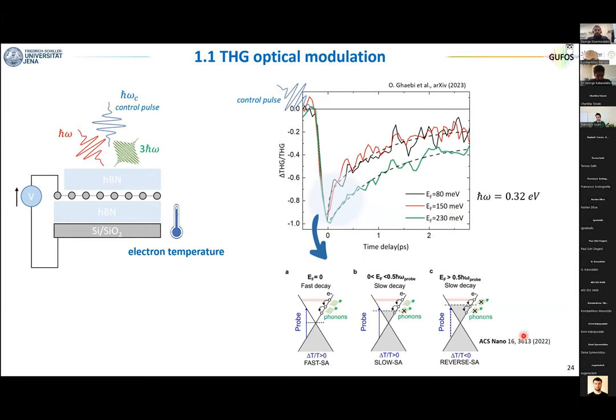This is again a work that we did with Giulio Cerullo. And the idea is the following. When you generate hot electrons, that means electrons that lie at high energy in the Dirac cone, if you want to dissipate energy to the lattice, you have to decay into the Dirac cone and emit an optical phonon. However, if you now start increasing the doping, there will be a level where the final state where the electron should go is already occupied by another electron.